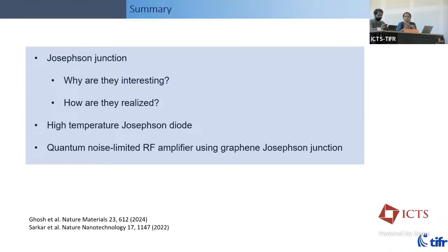Okay, thanks for that question. We were looking for tunability. In our experiments, we don't have smoking gun evidence of a time reversal symmetry broken superconducting state at the interface. Philip Kim has done additional experiments, and from measuring Shapiro steps they see some higher order terms in the current phase relationship, and they say that that's evidence. You should look at their paper, but briefly, they say they have evidence for a time reversal symmetry broken superconductor. We are doing some more experiments to try to find more direct evidence for broken time reversal symmetry. Right now, in our experiments, we don't have evidence for a time reversal symmetry broken superconductor.